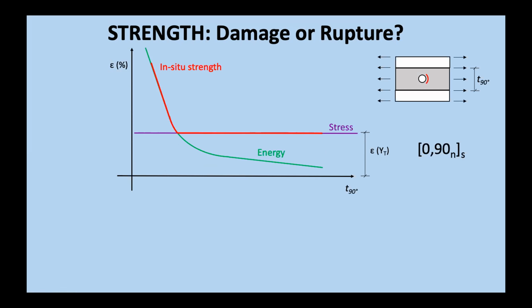But the question is that a couple of years ago, doing some numerical research, our predictions indicated that the appearance of one isolated debonding was not a function of the thickness, which was something that surprised us. So it means that, for instance, if we take a laminate with a very thin 90-degree lamina, we could have at this level of deformation of epsilon, one debonding, which would be independent of the thickness. So we would have, in accordance with the prediction, a similar value. In fact, as it is a non-homogeneous material, we would have an interval where this appears.